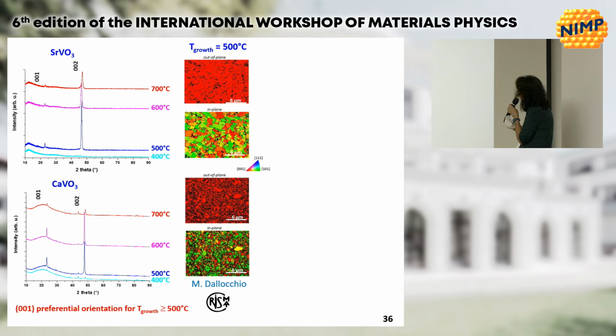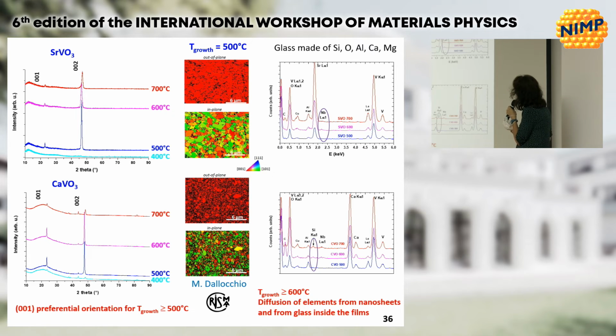We see a very strong orientation along the 001 direction for both materials, in particular at 500 degrees Celsius. Again, we can confirm the strong texturation by electron backscattering diffraction. We also checked the composition of the films. Since we are on glass, we can have some diffusion of elements of the glass into the film, and actually this is what happens. In this energy dispersive spectroscopy analysis, we see the presence of silicon and calcium in the spectra, indicating a diffusion of elements in the films.